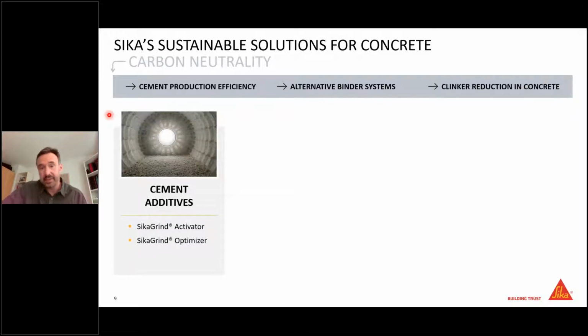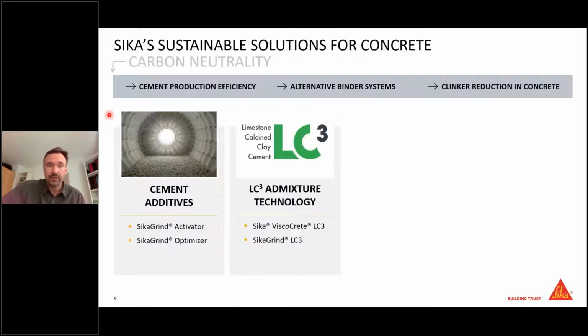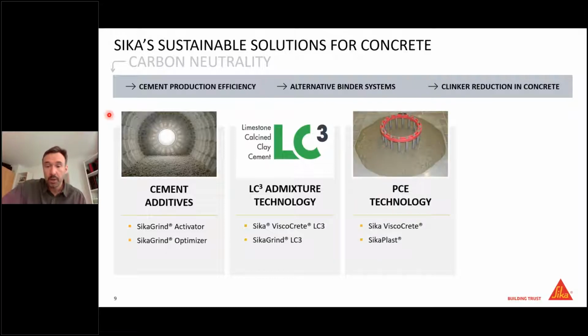For cement producers, less relevant for concrete producers, but just to let you know, cement producers are using our additives to increase the efficiency of the milling process, but also to improve the quality of the cement. We have developed an admixture technology that allows a very interesting future binder system, so-called LC3, but I will come to this in a minute. PCE technology is a key technology. We believe where many different targets can be met with.